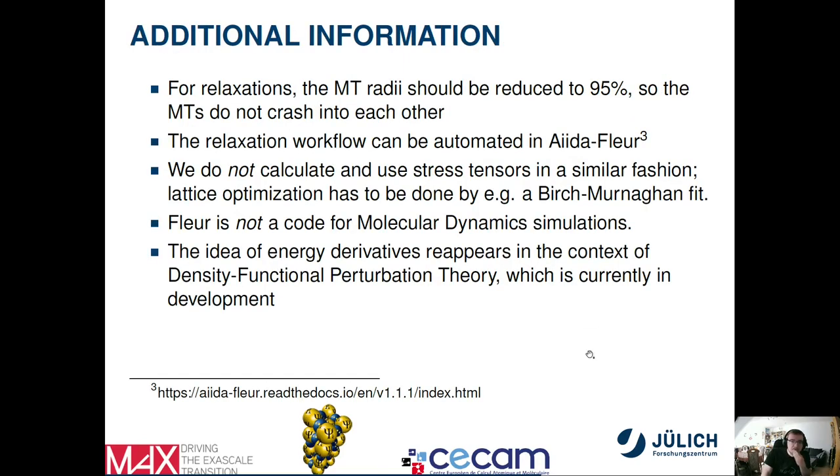So those are two very neat uses for forces. And I have some additional information for you in this context. If you want to do relaxations with the FLEUR code, you should always reduce the muffin tin radii to about 95% of what they are generated to at default. So when you have atoms that move towards each other in the relaxation, they do not crash into each other as fast. This is just something you do for safety.